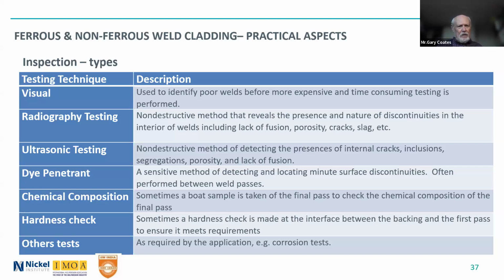Radiography, ultrasonics can be used, dye penetrant, especially for the smaller surface discontinuities. And often it's done between weld passes to ensure that there are no micro cracks there, micro fissuring there. Often a sample, we call it a boat sample, you take out with a grinding wheel to check the chemistry of the final layer, and then you can weld overlay back on top of it to bring it back. That is often done. Hardness check can be done, especially on the first layer, to make sure that you haven't got any embrittlement there, and other tests as required by the application.